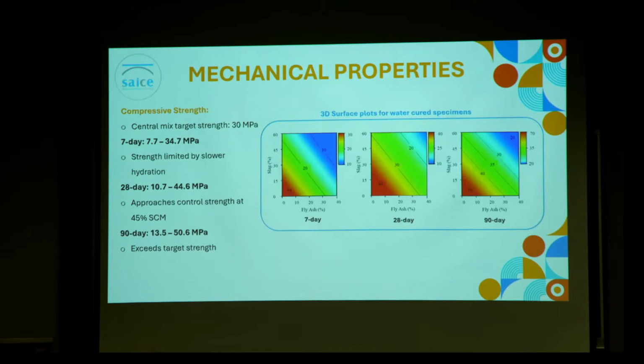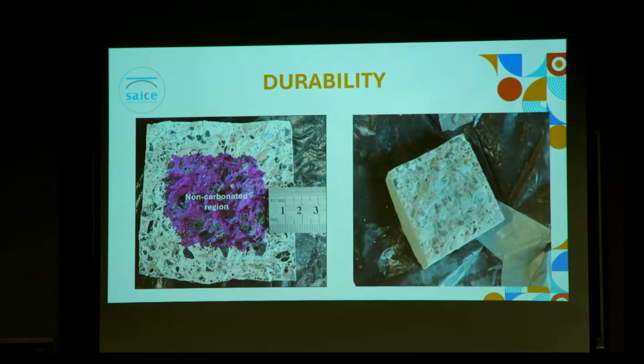up until 90 days. However, the mixes containing supplementary cementitious materials did not achieve higher compressive strength than that of the pure cement mix, which contradicted literature suggesting that fly ash and slag will enhance the long-term strength. However, a possible reason is due to the insufficient amount of cement available to react with the pozzolanic materials. Still, most of my mixes achieved around 30 MPa, which is perfect for typical home structures, offices, and other standard structures.